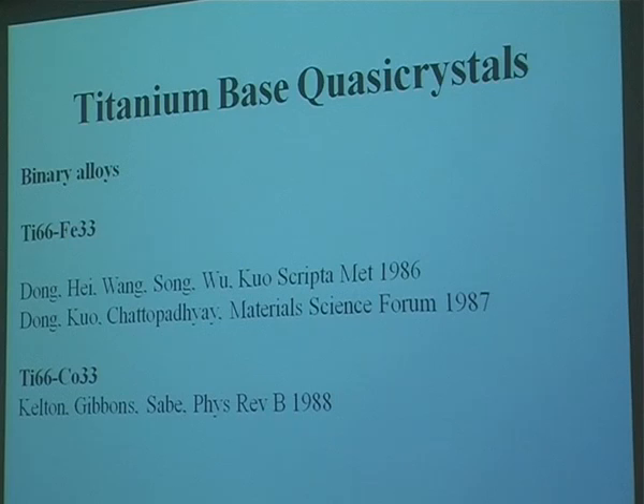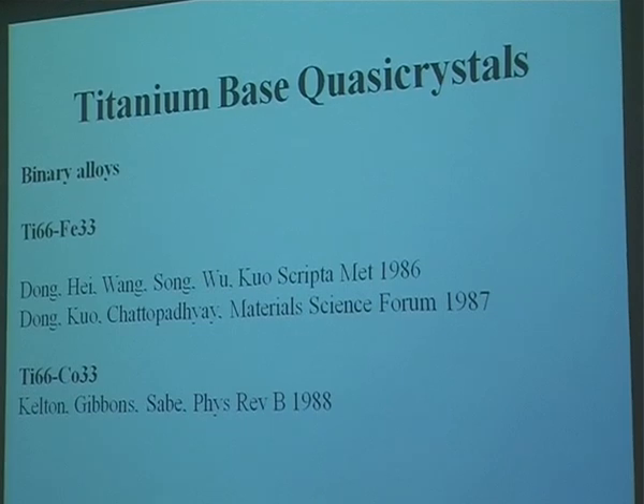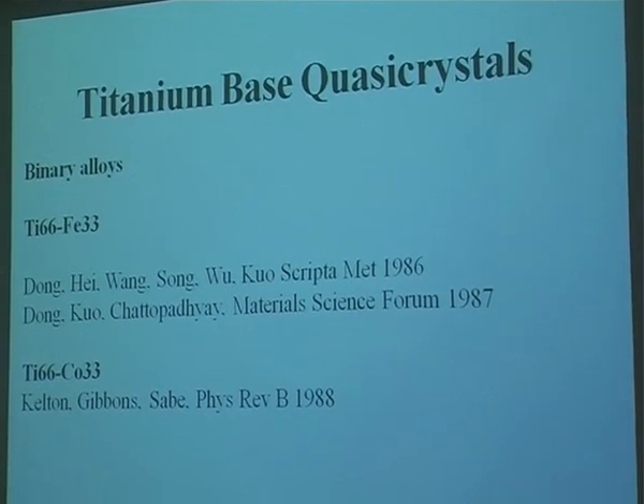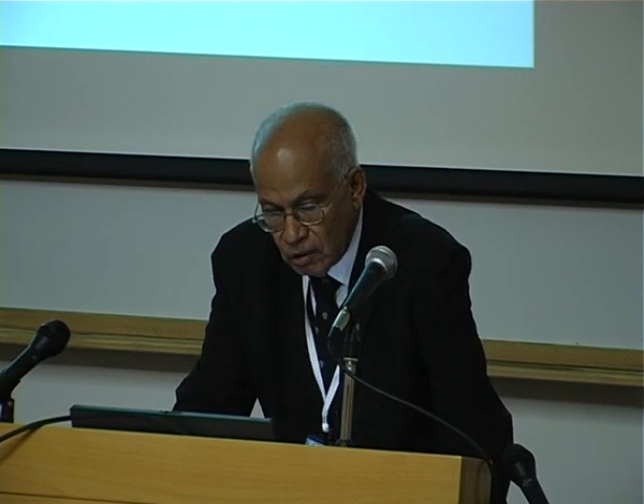And more importantly, he went on to work on titanium-based quasicrystals. Titanium 66, iron 33 in 1986, and then Kelton followed it up a little later with titanium cobalt. So this opened up a completely new field of titanium-based quasicrystals, when everybody again was working on aluminum quasicrystals. So you can see Ramchandra Rao paved the path for magnesium zinc aluminum alloys, if you like, and Professor Kuo paved the way for titanium-based quasicrystals.